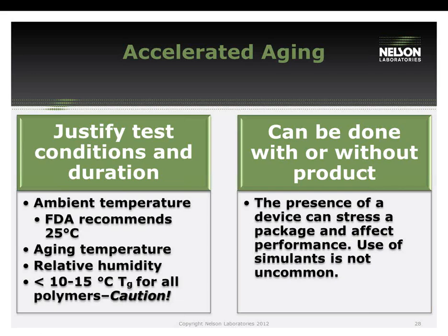The gist of the equation is that 1 year of real-time aging is equivalent to 46 days using a value of 55 degrees Celsius for aging and an ambient temperature of 25 degrees Celsius. So when you're doing your accelerated aging, it's important to make sure that you justify your conditions and duration.